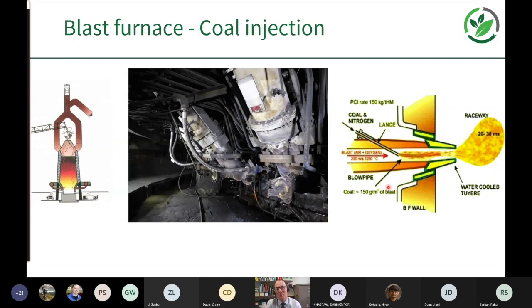Now I'm going to look a little bit more specifically into some of the work that I've done. I've been looking at injection coals. I must be quite honest that the push from the industry really is because coal injection is used to improve the efficiency of the blast furnace, so producing more for less material. It's been driven predominantly by this efficiency, the requirement to use different types of coals, coals that are economically more attractive.